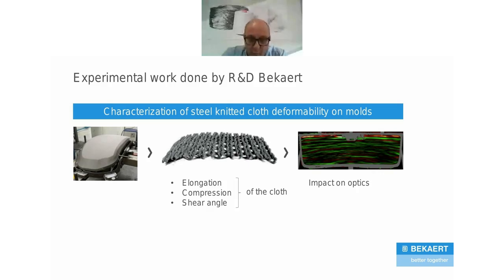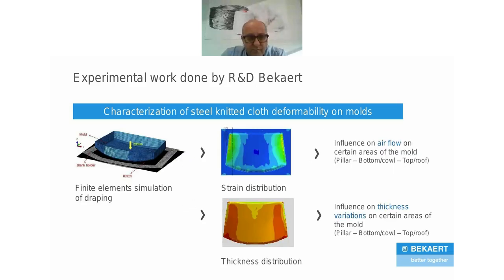If you put that on a mold, you will notice that in the middle it will be different than at the sides. So we did a kind of experiment, a finite element simulation of the draping, and there we looked mainly at the strain distribution and also the thickness distribution of the cloth on a mold. And what we saw is that if you put that on a mold, if you look at the colors, you can see that the colors are different on the pillar side, on the cowl side and on the top side. That means that you have a difference in airflow of the cloth and also of the air during the vacuum when you pick up the glass. So that can also impact the optical quality of the glass.